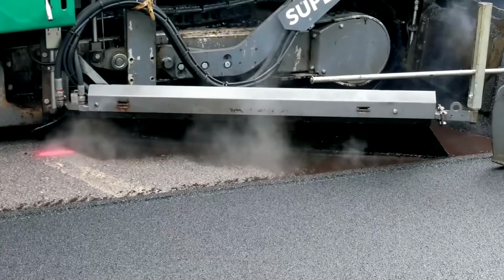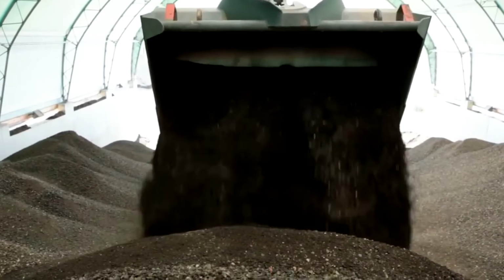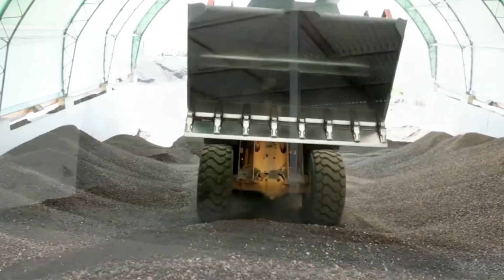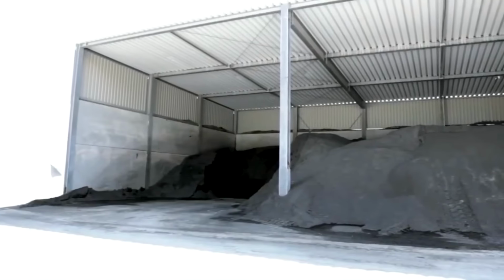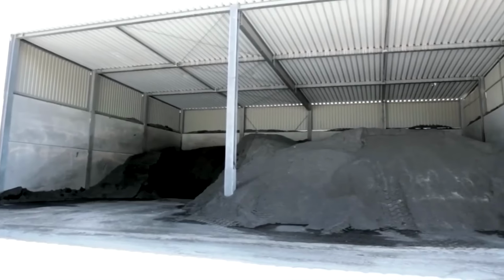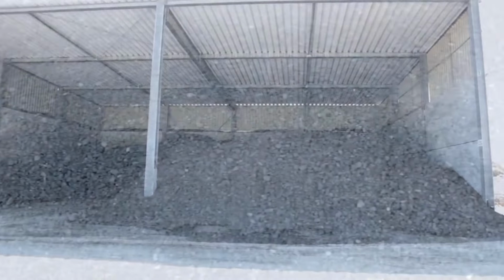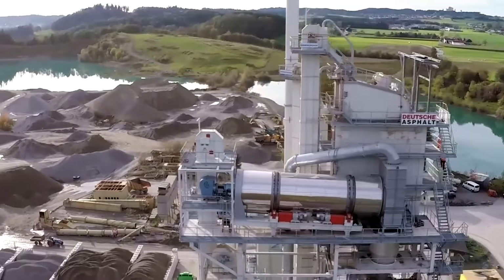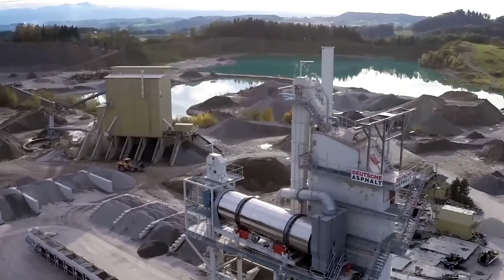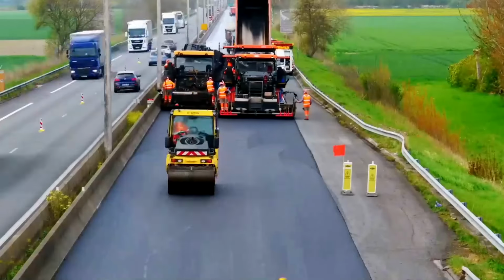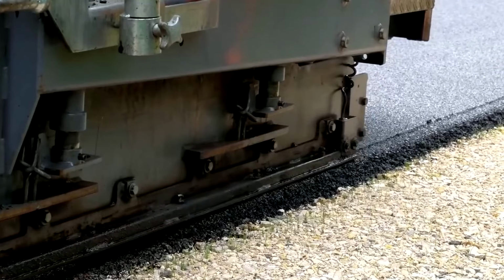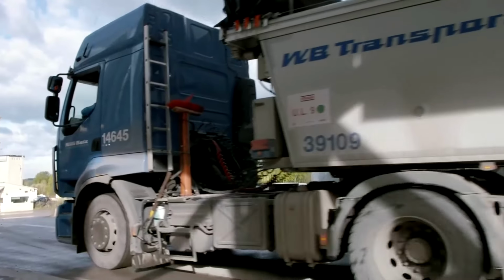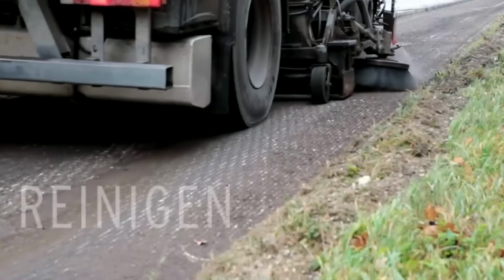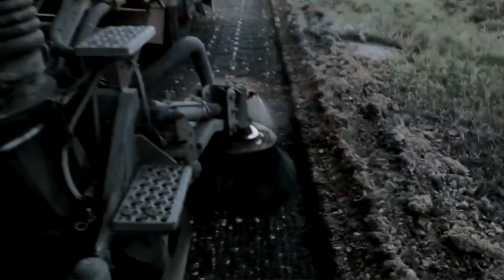At first glance, mixing old oxidized asphalt seems simple, but in reality, it requires the precise addition of a rejuvenator to restore elasticity. The material is heated gradually to prevent burning the aged binder, then combined with fresh aggregates and hot binder according to a pre-calculated formula. Modern plants can incorporate 30 to 60% reclaimed content without losing performance. And this is not the limit of efficiency.